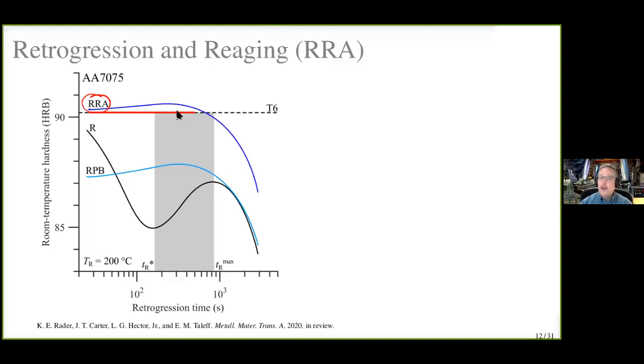All right, so we can go through these two steps. We get the strength here. Now I've drawn a second curve here. This is the retrogressed material, but instead of applying a full reaging heat treatment, what we've done is we've applied a simulated paint bake. What's the paint bake? Once the automobile body is produced, it's painted, and then it goes through an oven to cure the paint. That's called the paint bake.